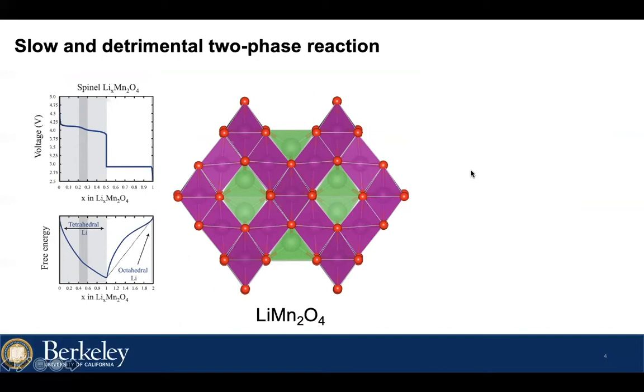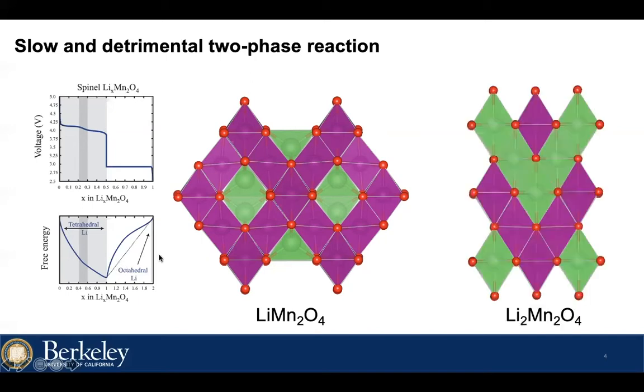So why is that? Let's take a look at the cycling curve and the free energy curve during cycling. You can see that when you lithiate the lithium manganese spinel, instead of going through a solid solution reaction, it actually goes through a two-phase reaction. The insertion of the lithium will form a well-ordered tetragonal phase, where the lithium all sits in the octahedral site. What makes it worse is the collective Jahn-Teller distortion in the tetragonal phase. In this phase, all the manganese are 3+, and it's a Jahn-Teller ion.